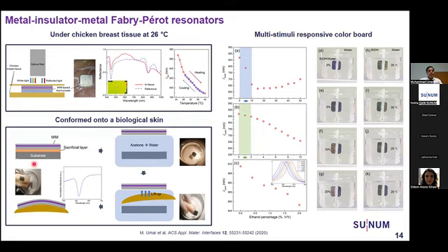We also utilized the same sensor. We used a sacrificial layer and then lift-off, and it was transferred onto pork skin, and at some temperature it again shows the resonance dip on the biological tissue. And here is the lift-off process. First, we remove it in acetone and then transfer to water, and then we scooped it onto the biological tissue. And then we also showed that this polymer can be affected by alcohol.